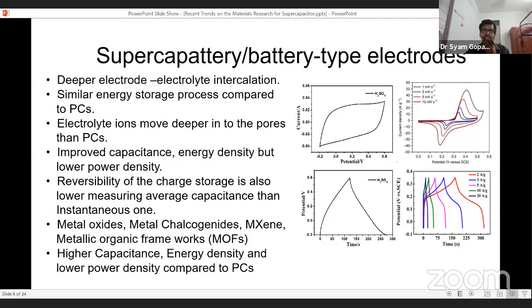That's why the term supercapattery has come. Again, the energy density of this material is not higher compared to battery material, but it is higher compared to a pseudo-capacitive or an EDLC material. That's why this new term, supercapattery, came. In a supercapattery material, what we can observe is a deeper electrolyte intercalation, then a similar energy storage process compared to pseudo-capacitance, then electrolyte ions can move deeper into the pores than in pseudo-capacitance. Improved capacitance and energy density, but lower power density. Reversibility of the charge storage is also lower, measuring the average capacitance rather than the instantaneous one.